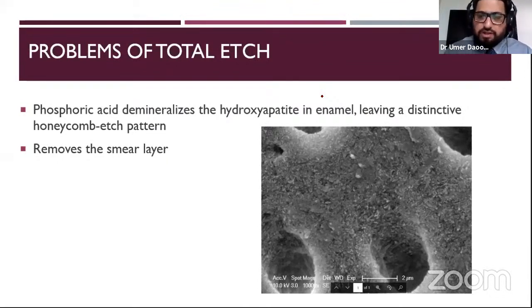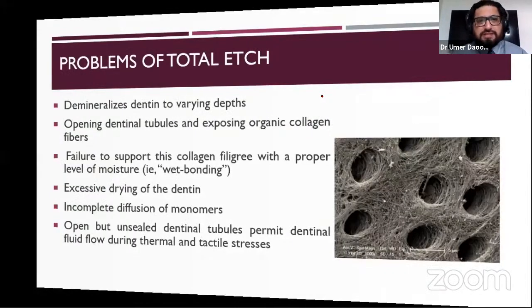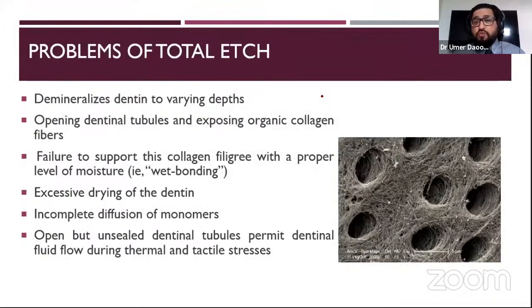The total etch, or the etchant, removes the smear layer. There's a bit of a problem of sensitivity, and it demineralizes the hydroxyapatite from the dentine and enamel. According to the Archives of Oral Biology, there was a paper that says that once all these structures are removed, they're never going to come back. You are removing the hydroxyapatite, or modifying it completely, forever in that place. So total etch comes with a bit of post sensitivity problem. It demineralizes dentine to varying depths because of the etchant being used separately. It opens up the dentinal tubules, exposing the collagen, and that's where the post-operative sensitivity issue happens.